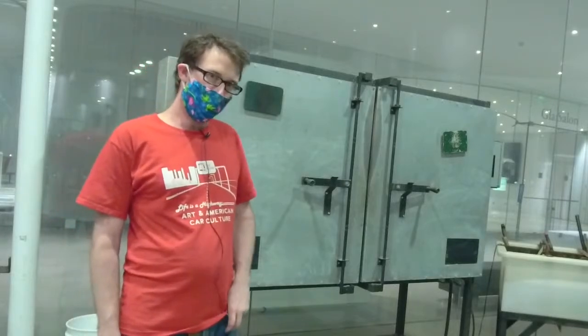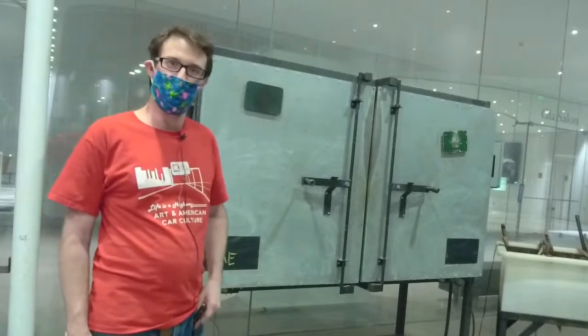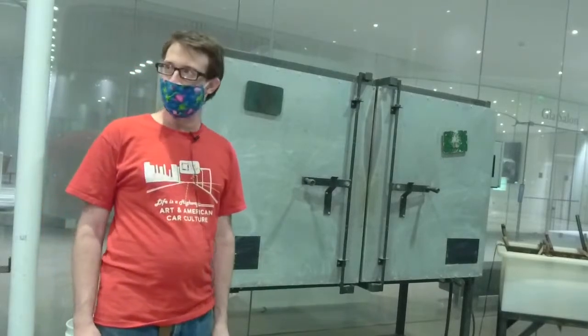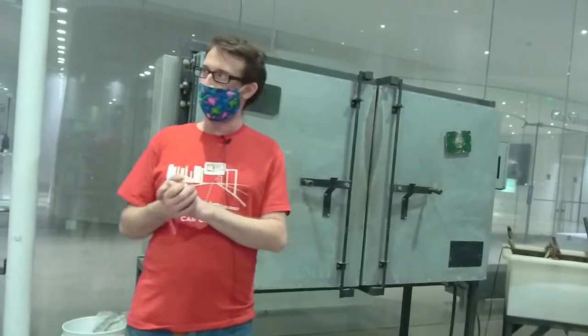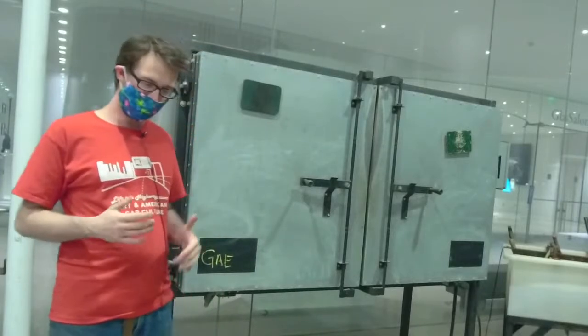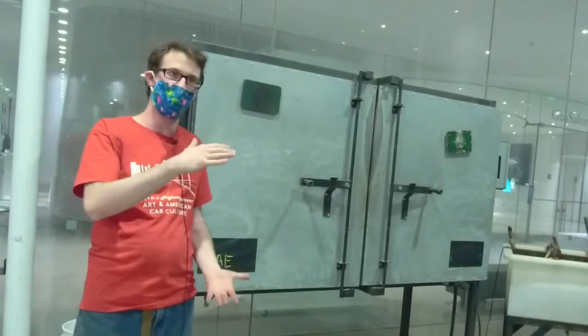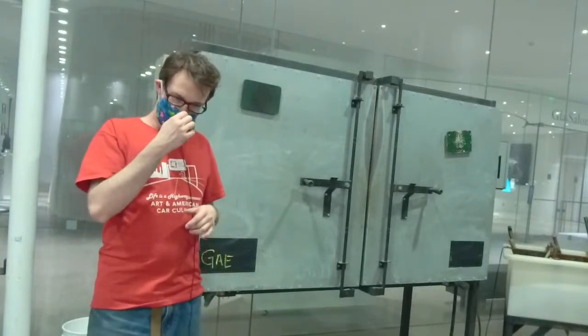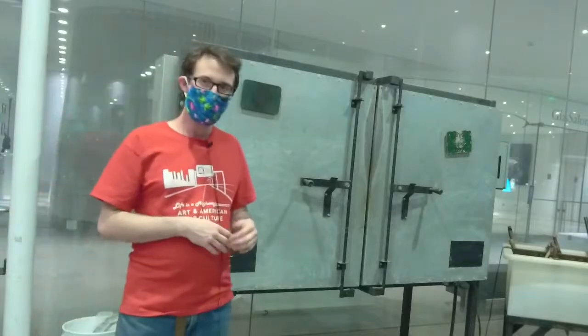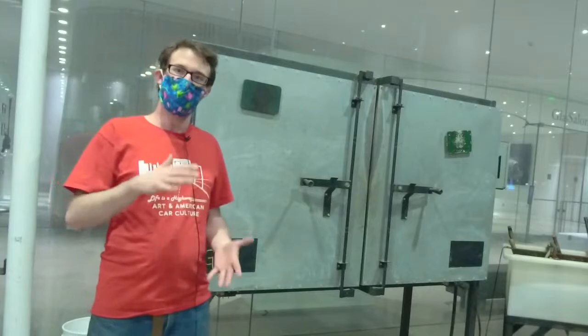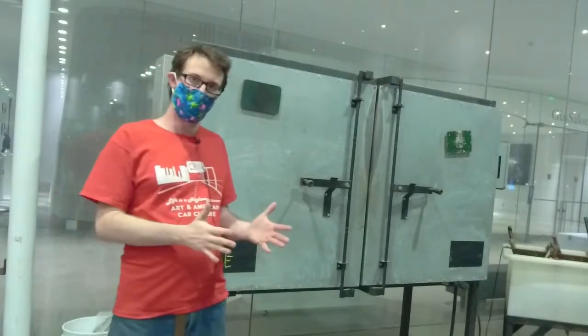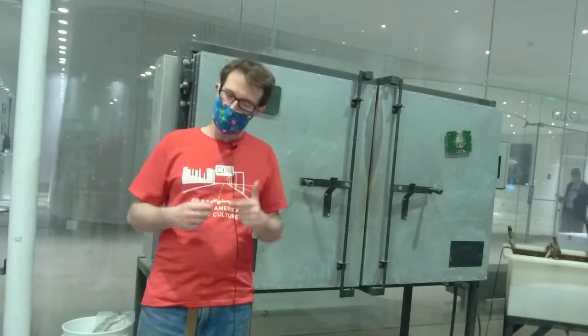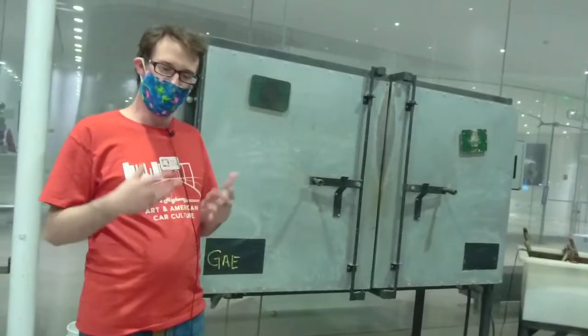So that's how everything in glass is made. You have to make sure that everything is annealed. For example, here at the museum, in front of our history section, we have a glass bench that is 3 feet of casted material. This was sand casted, and in order for this material to be fully annealed, it needed roughly about 11 months to fully cool from 918 degrees to room temperature. And there's actually a crack that's formed inside the bench, and that proves that there wasn't enough time taken to cool the bench.